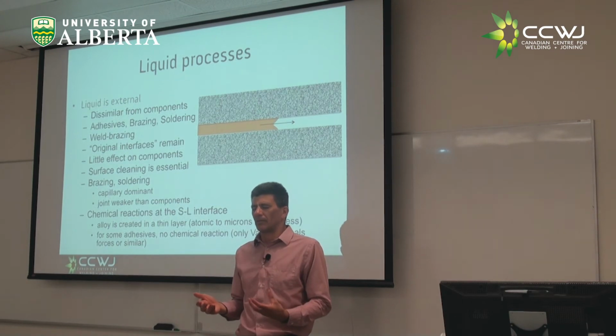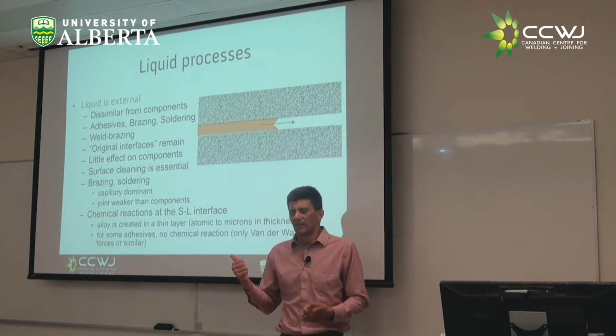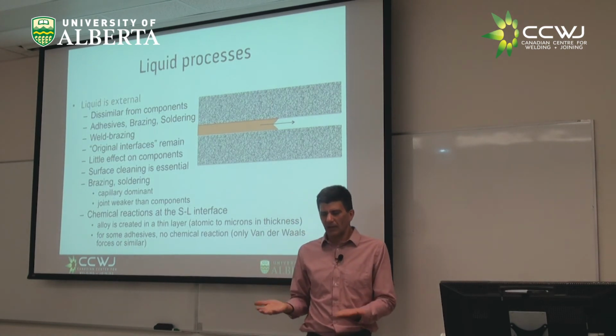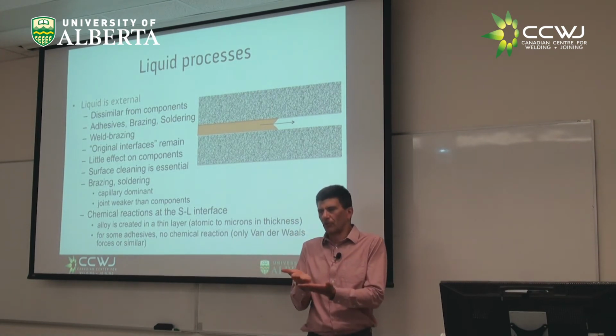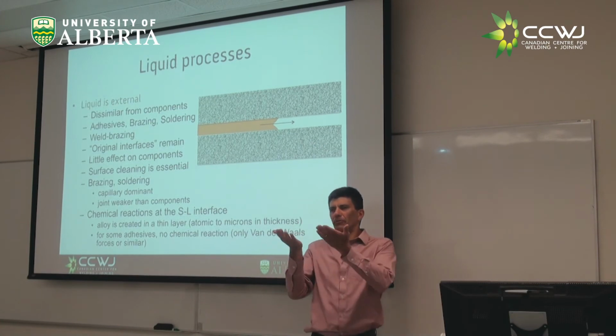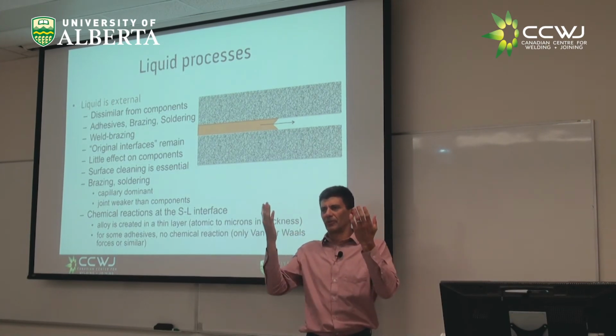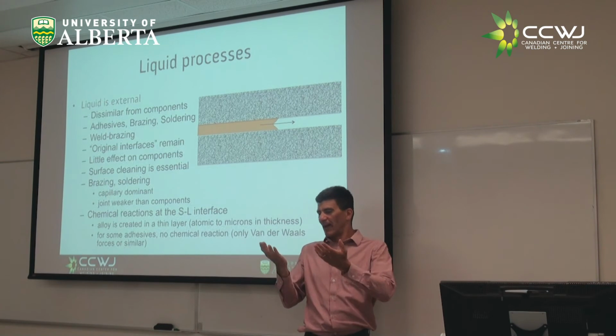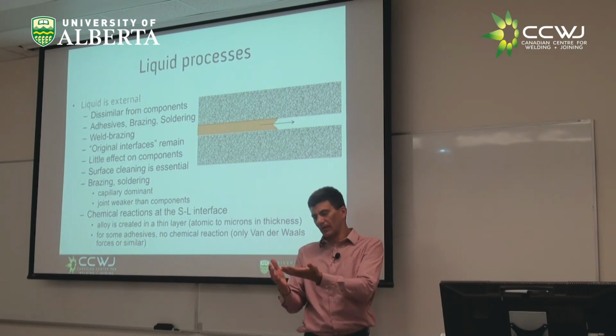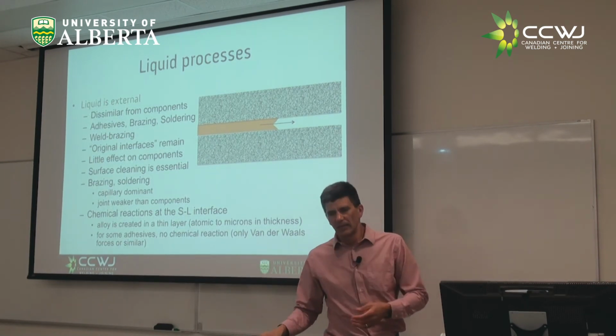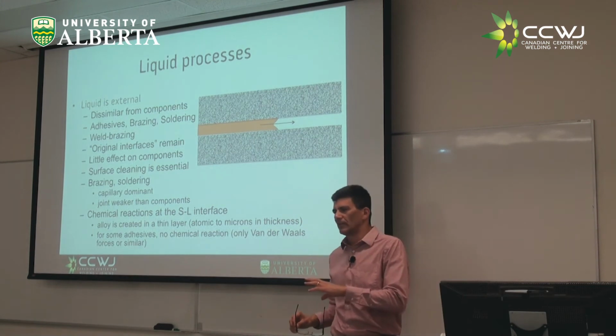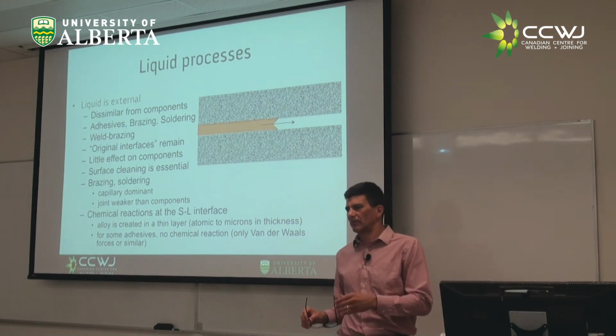Typically, these type of joints are weaker at the interface than the base material, and they cannot resist much temperature. So typically, if I do soldering or brazing, I can go up to the temperature of the solder or the braze, but I cannot go to the temperature of the copper. The copper can take a lot of temperature. But if I go that high, I'm going to remelt my solder or my braze, and things are going to come apart. So those are pros and cons. There are ways around it.